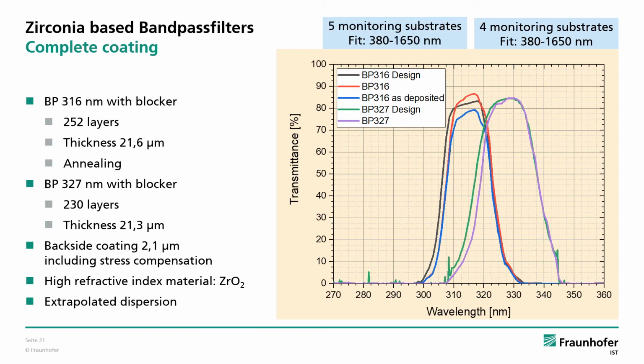The shape of the bandpass stayed in good match even for the complete coating with more than 200 layers, which is shown in this graph. It also includes a backside anti-reflective coating with 2 micron stress compensation by silicon oxide layer. For the 316 nanometer coating, blue curve, the absorption was slightly underestimated during the design in black curve. Annealing of the filters brought the transmittance in red line over the threshold of 80%. For the 327 nanometer filter, no annealing was used.